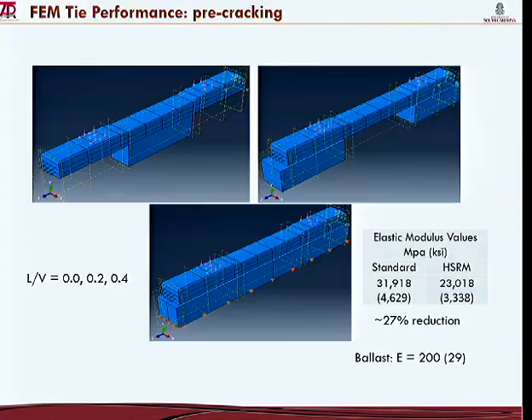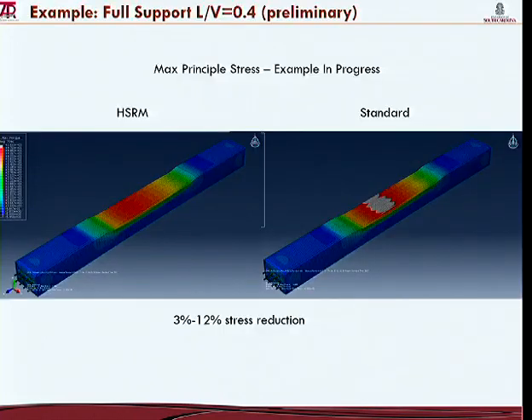Parametric studies through finite element analysis. I'm not going to bore you with the details of the model, but basically what we did here, we took the values straight out of our lab testing measurements, and we also applied some lateral load, L over V, 0.2 and 0.4. And the HSRM showed anywhere from 3 to 12% lower stress. This is ongoing work. We just started it. This is still linear. We're moving into looking at the post-cracking behavior.